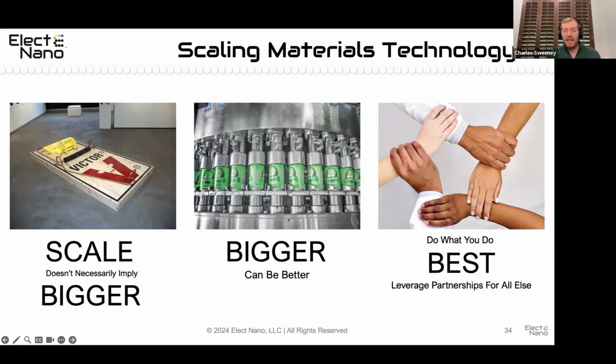The other thing is, bigger can be better. A lot of times when you're in grad school or in a startup mode and you're trying to do something on the very, very small scale, you're MacGyvering a setup to prove out the concept without costing a lot of money in capital equipment. And it leads to a lot of compromises, and your results may be skewed, or you may get very inconsistent batch-to-batch results. Don't get discouraged about that, because there are many challenges with scaling process technologies, but one of the cool things is when you can really go bigger, you have a lot of opportunity to control the process and go very quickly, and actually the quality can get better as speeds and throughput go up.